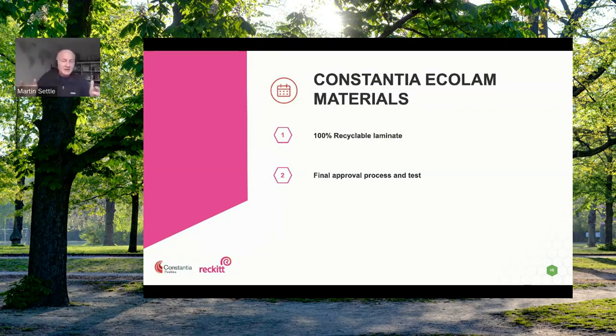So this led us, through the development partnership with Constantia, through the work we did with RecyClass, from the assessment we did of external work, to a material mix with Constantia and looking at the Ecolam. We tested it, we retested it, and we rechecked it. We confirmed recyclability and its sustainability criteria, both internally and with the RecyClass tool. And we also checked that externally with a recommended third-party recycler auditor to confirm the RecyClass results. And we ended up with a material that works for us as technically recyclable and meets all the requirements and has been certified by a third party to be recyclable for claims on pack.